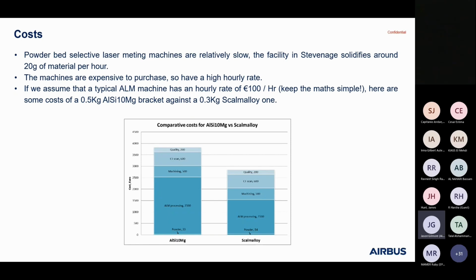So if we look at a TMTC bracket in aluminium silicon 10, the cost of the powder without any factor for wastage is really very low. Typically, when we used to buy aluminium silicon 10, it was around about £55 a kilogram. So half a kilogram of bracket, a bit of wastage, it's probably 30 to 40 pounds per bracket. Now, if you're going to deposit half a kilogram of material at 20 grams an hour, you're looking at around about a 25-hour processing time. You could argue that you've got a setup time and time to allow the machine to cool down would add further cost. So that's £2,500 of processing time, some machining, some scanning, some quality time attributed to the paperwork and the validation of the part.